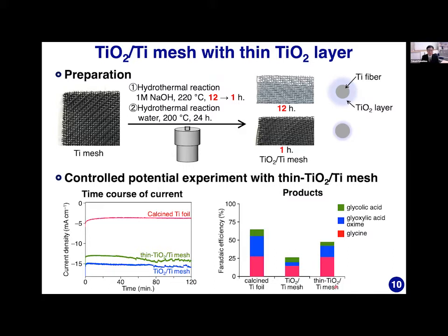And it was found that the thin titanium oxide titanium mesh gives a large current density, the same as the titanium oxide titanium mesh, and a high Faraday efficiency for glycine production comparable to that given by calcined titanium foil.